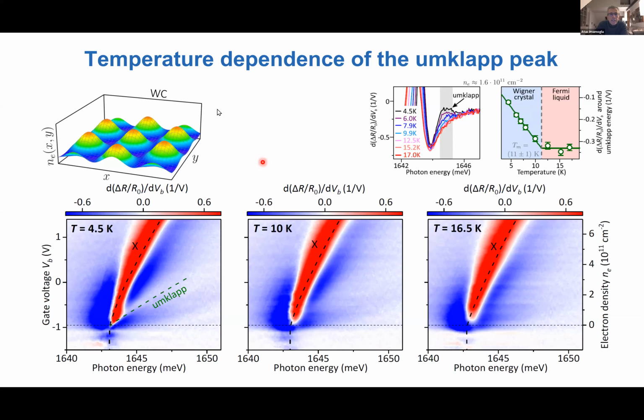Is it possible to think about this crystallization in a trion framework as well? In principle, if you are looking at the attractive polaron, then the answer is yes. In the case of the attractive polaron, you can argue that when you excite the system, you generate a periodic array of trions. Now, the point is that, as far as we can see, our crystal is not spin polarized, or at least we cannot see its spin polarization. It might be affected by the fact that we do have an optical excitation. And the effect of lack of spin polarization on the repulsive polaron.